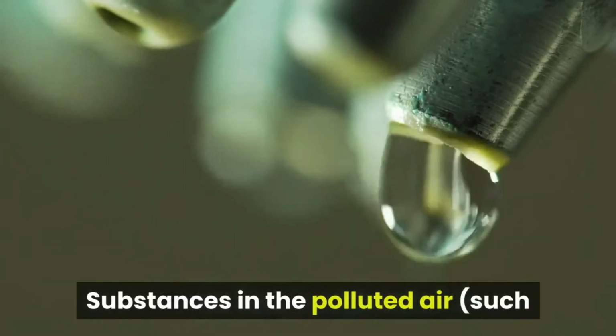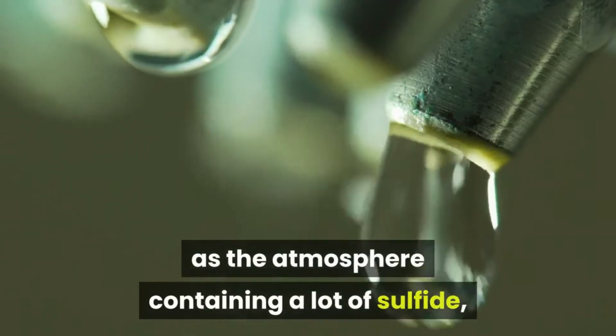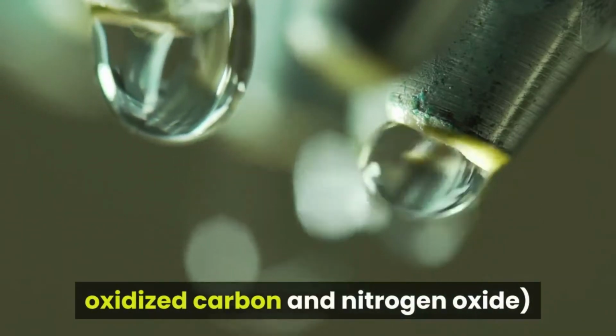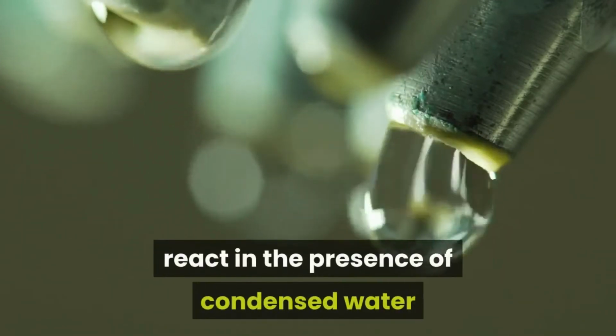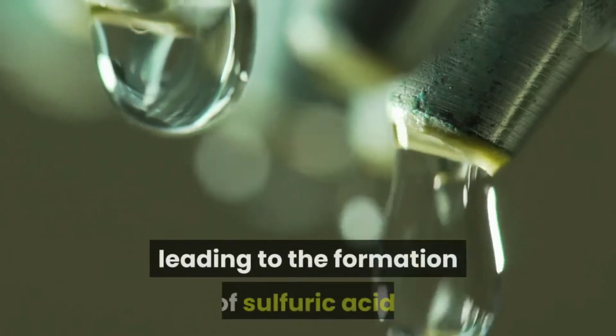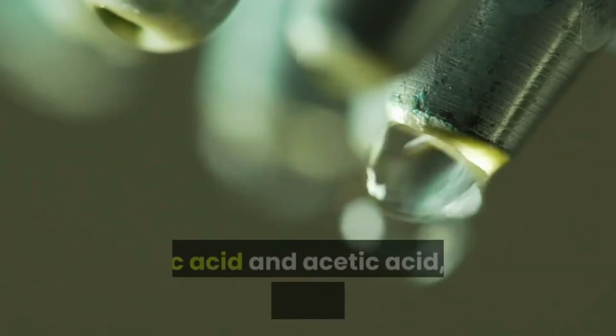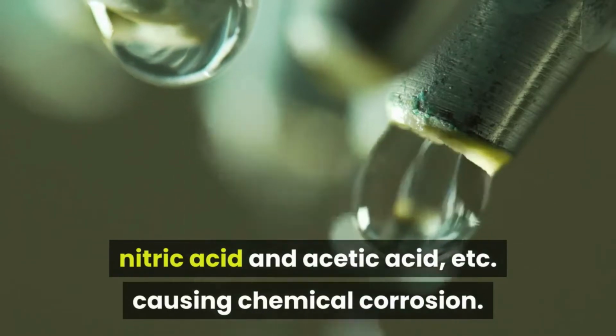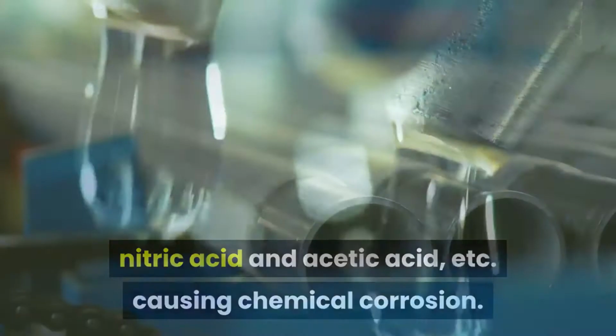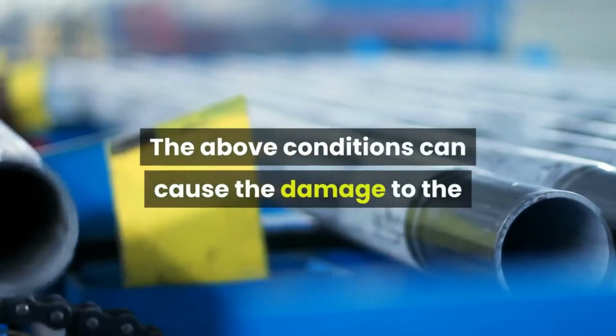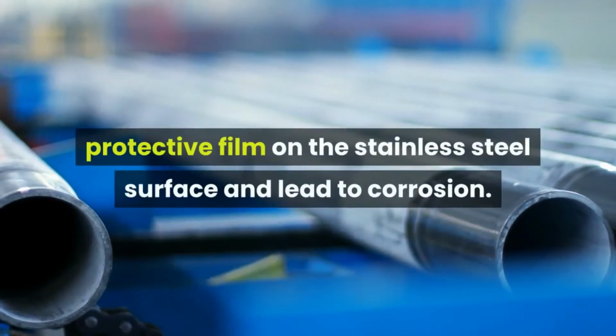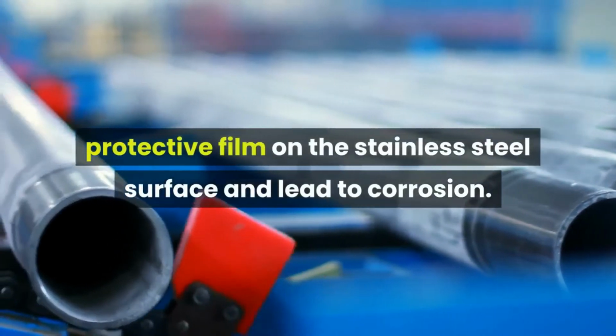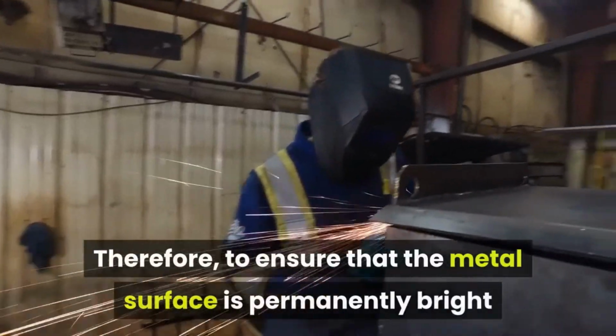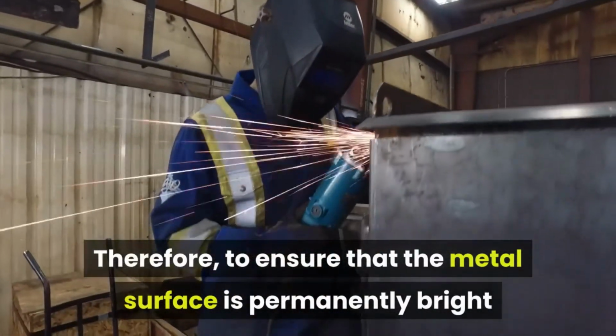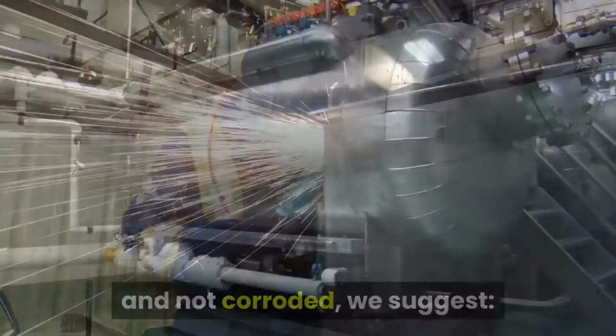Substances in polluted air, such as an atmosphere containing a lot of sulfide, carbon oxide and nitrogen oxide, react in the presence of condensed water, leading to the formation of sulfuric acid, nitric acid and acetic acid, etc., causing chemical corrosion. The above conditions can cause damage to the protective film on the stainless steel surface and lead to corrosion.